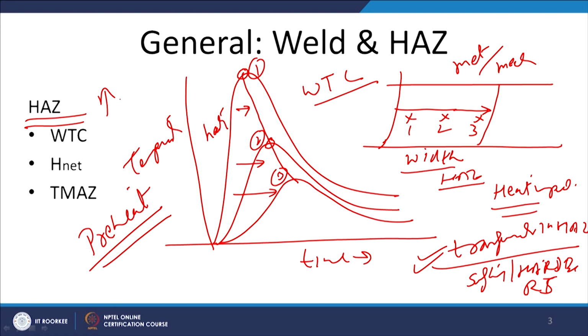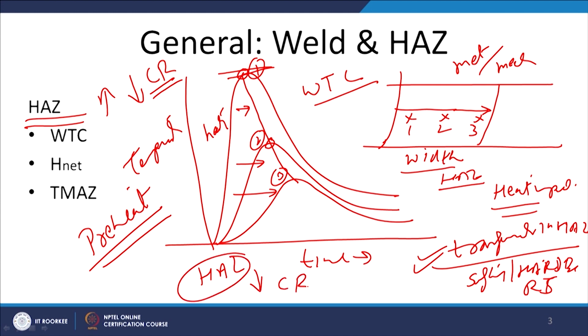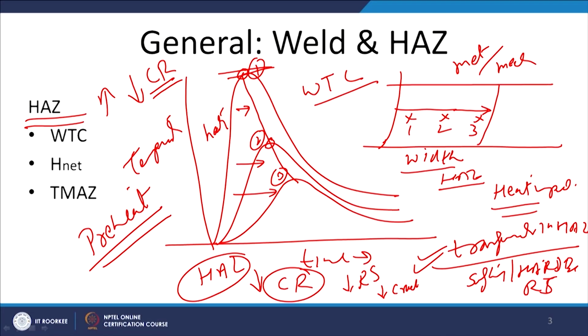Preheating will be increasing the peak temperature of a particular location, but it will be reducing the cooling rate being experienced. So, preheating of the base metal during the welding will help to change the weld thermal cycle favorably. However, it may increase the HAZ width, but it will reduce the cooling rates. Since the cooling rates, especially in welding of steels, are more troublesome, preheating sometimes helps in reducing the residual stress development, and it also helps in reducing the cracking tendency and the embrittlement as far as the heat affected zone is concerned, and this happens through the control over the unfavorable metallurgical transformations.